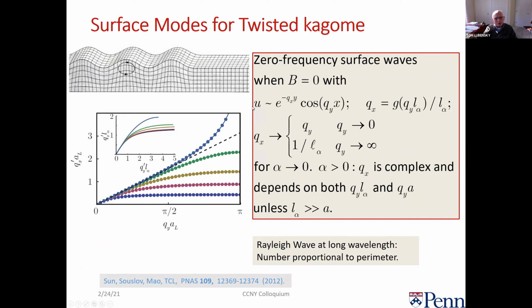Well, I'll have a displacement U, which decays into the Y direction and is periodic along the X direction. Yeah, this is correct. So when I go to the long wavelength limit, my lattice should have exactly the same mode that a continuum elastic solid has with a bulk modulus that vanishes. And sure enough, every one of our curves of the penetration depth here, the q_x, y terms. So this is an exponential. This is the inverse penetration depth. And this is the wave vector along the surface, which is along Y.